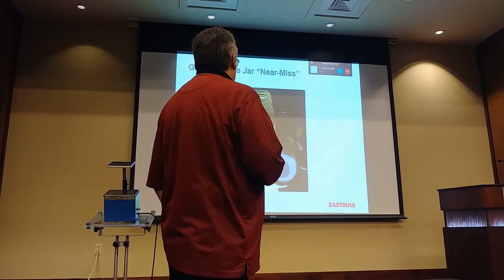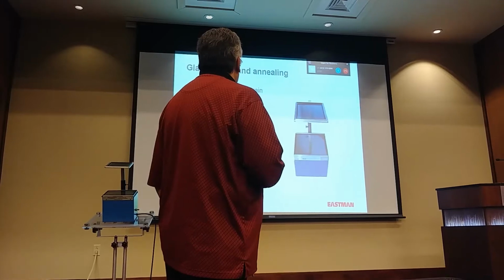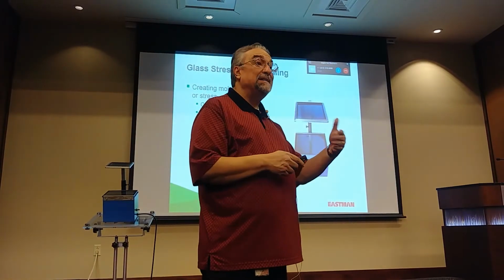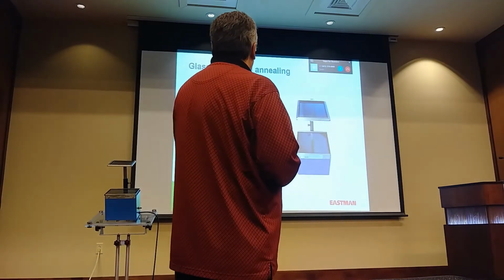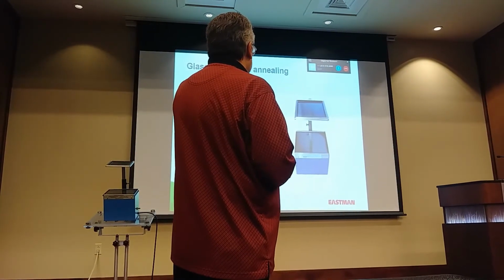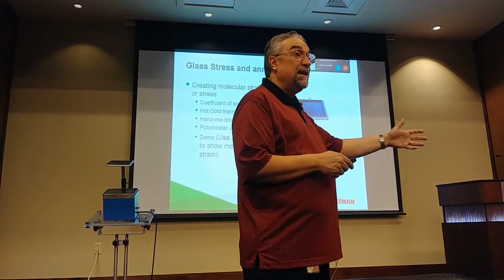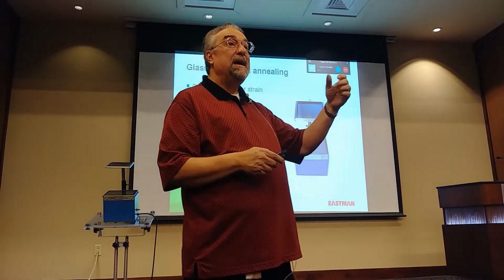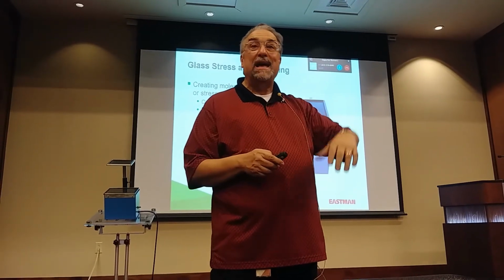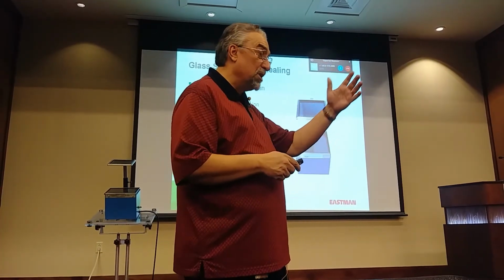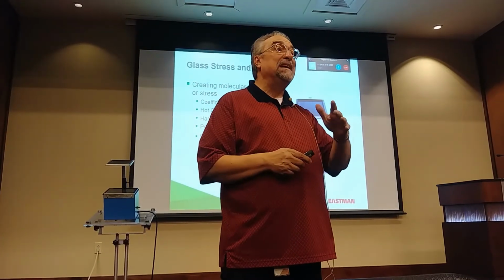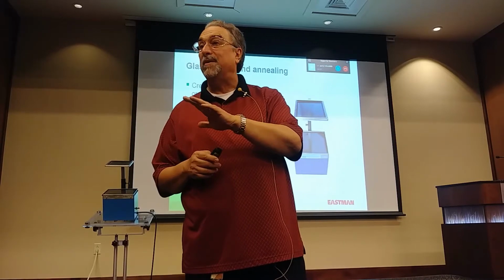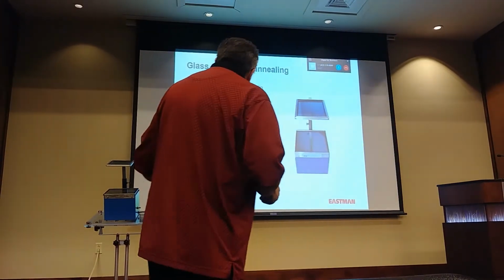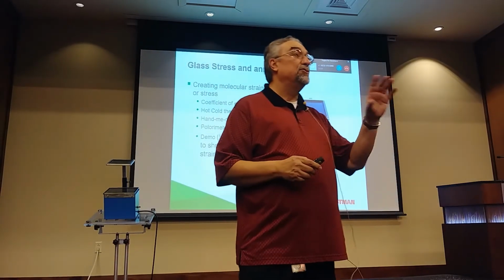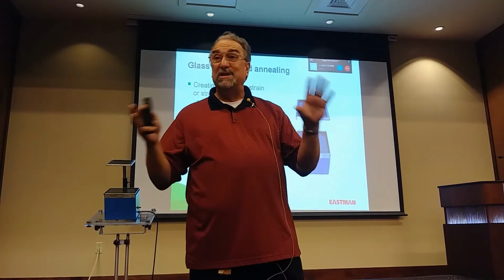So that's how you can absolutely overstress a piece of glass. Now, believe it or not, stress in glass is visible. And this hot-cold thermal shock is important even to a piece of Pyrex, because you can get away with heating up a piece of glass and cooling it down, heating it up and cooling it down, and heating it up and cooling it down. And you may not visibly see any change in that flask whatsoever. But I will show you eventually on a polarimeter exactly what molecular strain looks like. And it can build up over time.